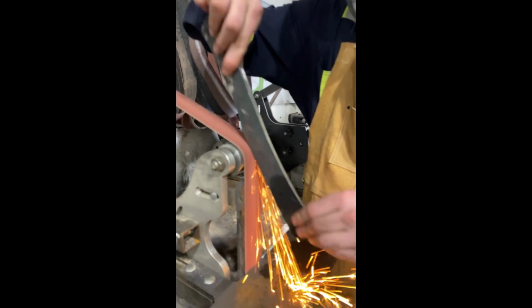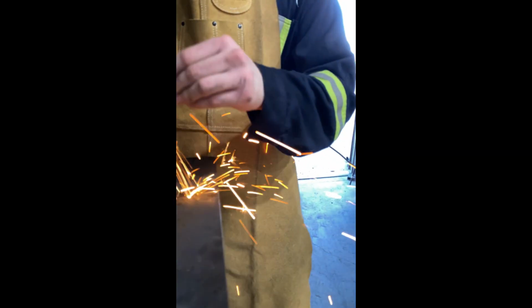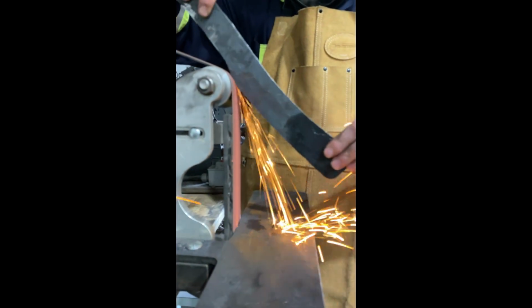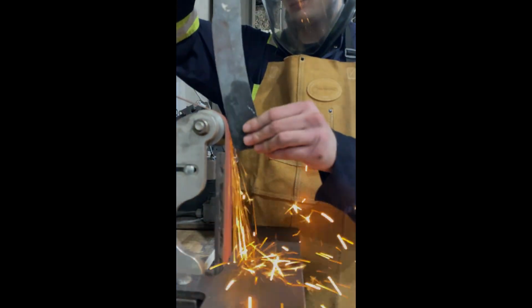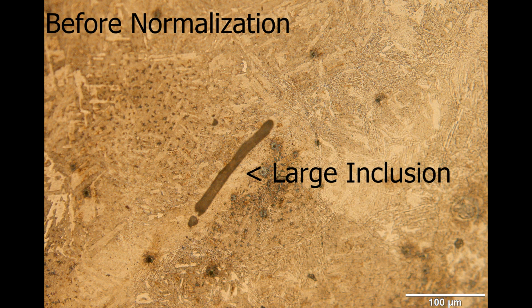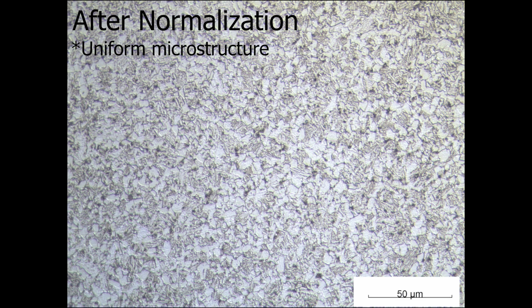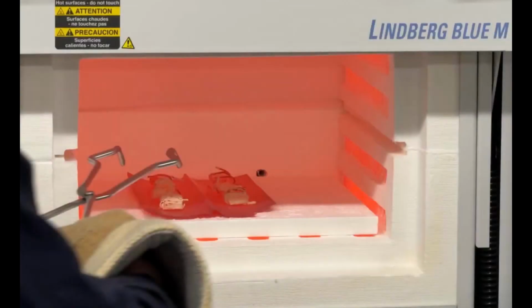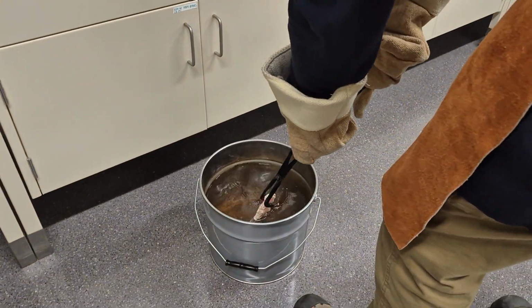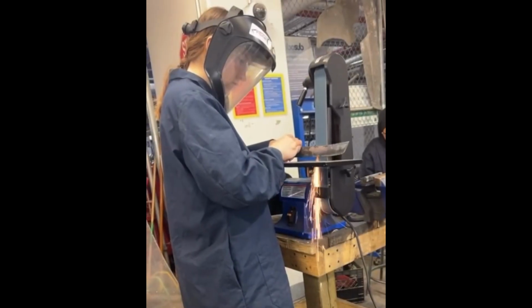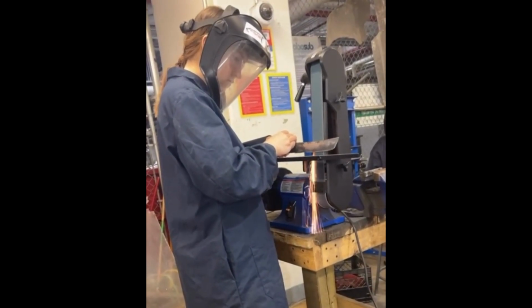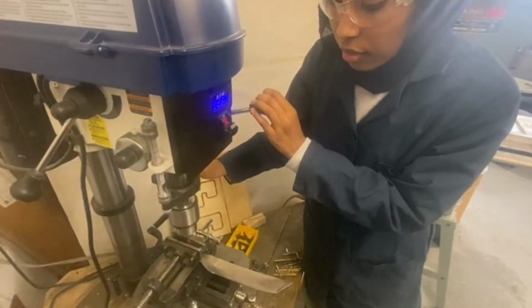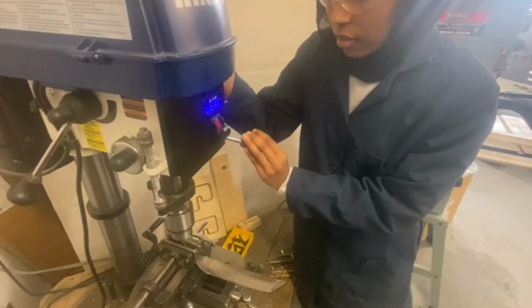style. Once blades were in the desired shape, we quenched the blade to room temperature, ground out the oxide layer and hammer marks with 120 grit paper. Next, the blade was normalized at 950 degrees Celsius for 15 minutes and air-cooled to room temperature to correct any deformities from forging. Afterwards, we coated in clay, then austenitized at 850 degrees Celsius for 30 minutes. Then, we partially cooled for 5 seconds in room temperature water before allowing it to air-cool. We then ground the blade using 120 grit sandpaper to remove any surface impurities and improve aesthetics. Using a drill press, we pinned holes in the blade and assembled the handle.